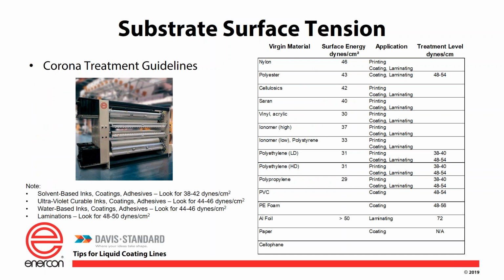Here's one I like to put up. I know Tom's going to talk about this quite a bit, but what I look at on the coaters is these are the basic films in their virgin modes, and what are the surface energies before they're treated. And then I'm looking at either printing, coating, or laminating. What is the actual level of treatment that we need to apply these different coatings, whether they be water-based or solvent-based coatings? So you can see here with the different substrates, as I mentioned earlier, we're looking at surface energies. What am I applying? Now I can see I do need to treat these webs before I could actually apply a liquid coating to them, and how much I've got to apply, which I'll let Tom and them guys go through all that with you. Okay. Next,